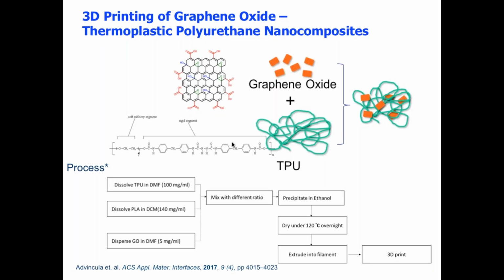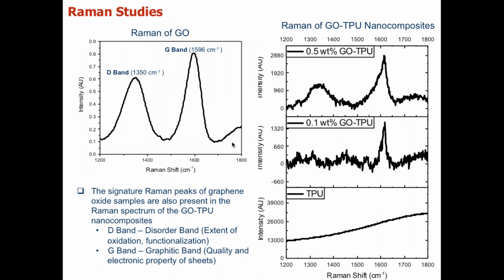So in this project, we have used the combination of graphene oxide as a reinforcing material in thermoplastic polyurethane. We first prepared the graphene oxide and thermoplastic polyurethane together with the polylactic acid compatibilizer by solution method. This allows us to prepare a very homogeneous mixture, which we can then evaporate the solvent and end up with a polymer material that we can prepare a filament. To verify the presence of graphene oxide, we use a technique called Raman spectroscopy to look at the D and G bands of the graphene and the oxidation state that it was used in the mixture.